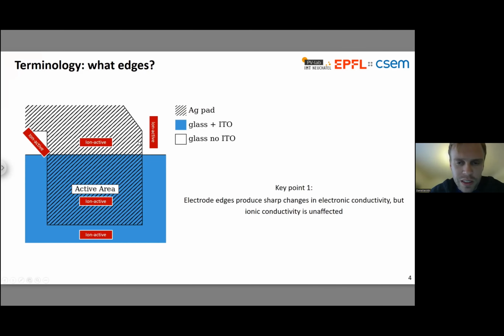And the key point that's emerged out of this investigation is that we have to be very careful what we mean by active area with these perovskites, because perovskites are not just semiconductors, and wonderful semiconductors they are, they're also mixed conductors, which means they have an ionic component to the conductivity. And we're not really thinking of that when we make this designation between active and inactive area. So although these electrode edges at the boundary of our active area produce a very sharp change in the electronic conductivity, they don't affect the ionic conductivity, so ion conduction happens, as far as we know, primarily through the perovskite layer. So wherever you've got perovskite, you have lateral ionic conductivity. And what that means is that your entire substrate is ionically active. This distinction of active and inactive areas simply doesn't apply when we're also thinking about ions.